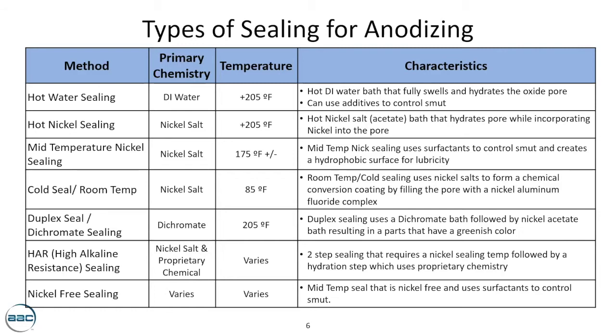Cold seal, or room temp seal. Cold is a relative term, but the intent of this seal is to be done at a room temp temperature of at least 85 degrees. So obviously in winter, you may have to incorporate heaters into that seal, but as a rule, it's done at a much lower temperature than its counterparts of mid-temp and hot nickel. But the logic is the same, we're trying to incorporate nickel into the anodic coating, but in the case of a cold seal, we're doing that in 2 separate steps. The first step will be the cold seal step, where we're using a nickel salt with fluoride to go into the anodic pore. That step is followed by a hydration step, which is essentially the hot water sealing that you're seeing at the top of this chart.